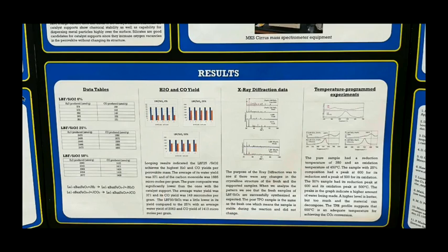The TPO results indicate the same, as the pure sample requires a lower temperature than the composite samples to peak and make carbon monoxide. The higher peak temperatures are related to the formation of cationic vacancies during the sintering of LBF and silicon dioxide. This also shows the increase in oxygen vacancy energy as the vacancy in the lattice gets larger. To maintain electrical neutrality during the cation vacancy, one of the nearest metals acquires two positive charges. And in this case, it's the iron and lanthanum, and this causes a shift in the perovskite reduction temperature.